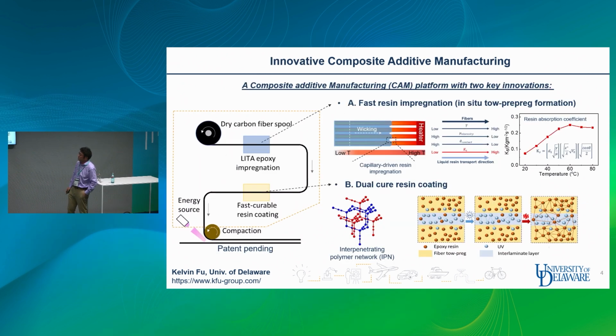So here we developed this mechanism to solve the problem. The first one is that we introduced an epoxy impregnation system to enable fast resin impregnation. And we call this in situ towpreg formation.